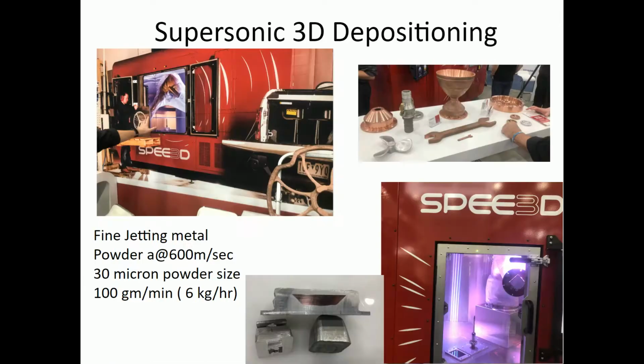The next metal AM process is supersonic 3D deposition by the company Speed 3D. Here the kinetic energy of fast-moving 30-micron particles moving at 600 meters per second bond together on impact. This has fairly fast production rates of about 6 kgs per hour. This is a great application for copper. Post-machining is needed to clean up the irregular surfaces. An interesting example shown here is an aluminum shell with a copper filling. Many interesting examples presented here to the right of the screen with both aluminum and copper.